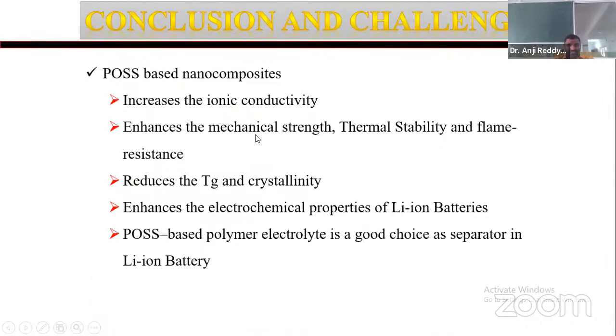What are the conclusions? After adding this POSS-based nanocomposites, that increases the conductivity, mechanical strength, thermal stability, flame resistance, and reduces PEG crystallinity and enhances the electrochemical properties of the lithium anode. And finally, this POSS-based polymer electrolyte is a good choice as separator in lithium batteries. But with ionic liquid, there is only one problem, that is mechanical stability. Otherwise, ionic liquid based polymer electrolyte is also very good. But that we can rectify by using this fast based ionic liquid.